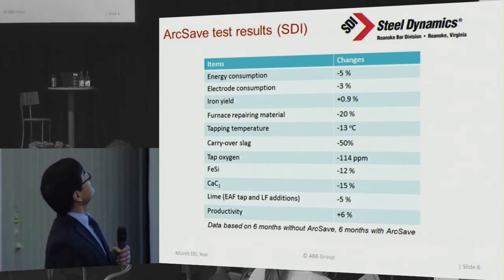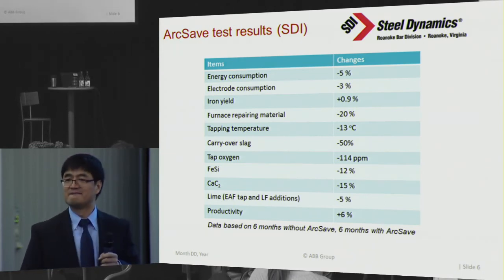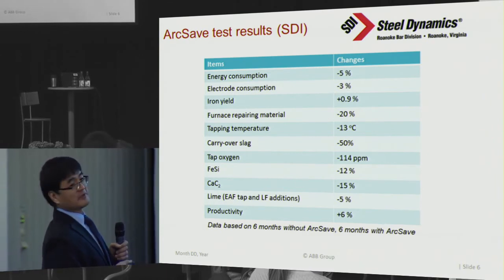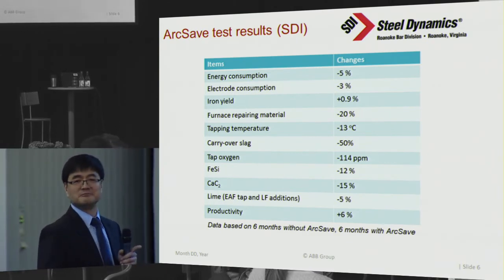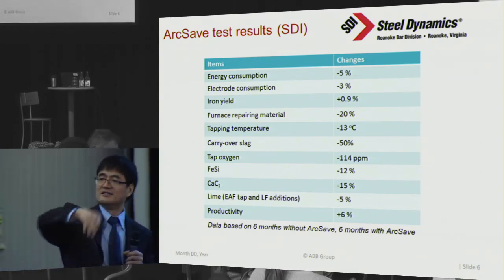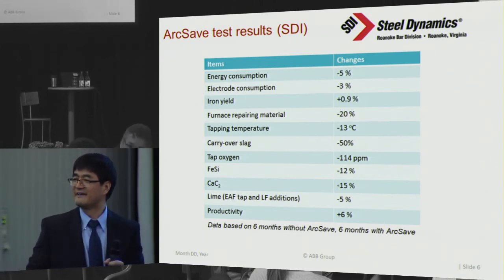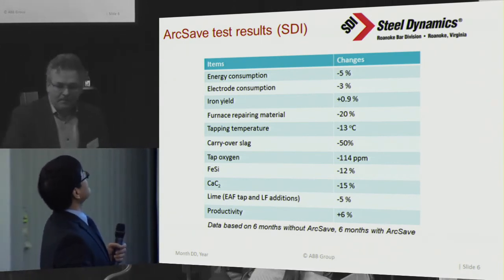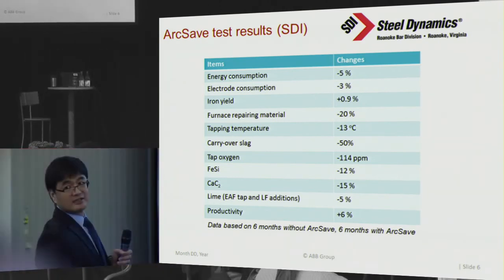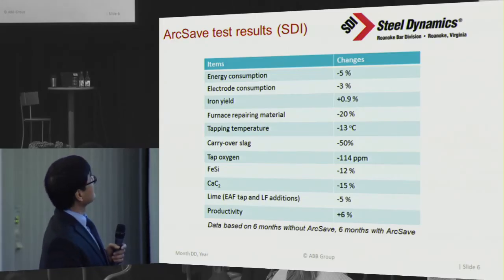Energy is 5%, yield almost 1%. That is $3 per ton of saving. Refractory repairing material is also reduced because the superheat is reduced in the slag line. Carryover slag, as I said, is 50%. Tap oxygen is also reduced, 114 ppm. But the carbon is not changed too much, about 0.002. That means that is also an alloy saving. Productivity increased by 6%. Okay.